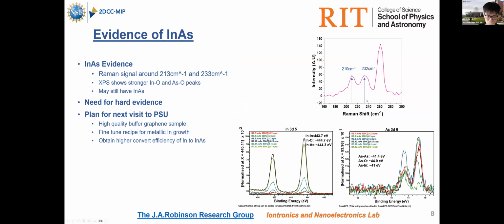by these two peaks. However, the XPS does weaken our evidence a little bit, because as you can see from both the indium peak and arsenic peak, since the arsenic oxide and indium oxide, so the indium oxide peak and the indium arsenic peak are close together. So here from the XPS, we do see a really strong oxide peak signal that might